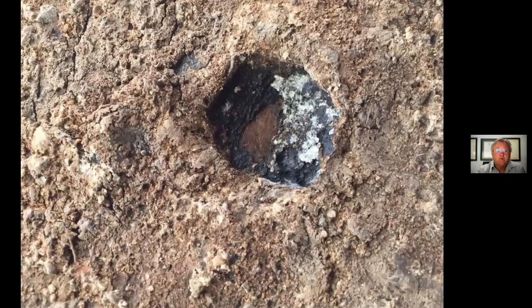Due to the higher temperatures and the non-sifted backfill, this coating actually then was subject to penetration, and there you can see the hole left by a stone that had become embedded in the coating, setting up a coating defect. And this pipeline had literally hundreds of defects.